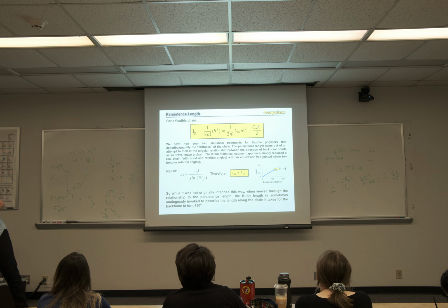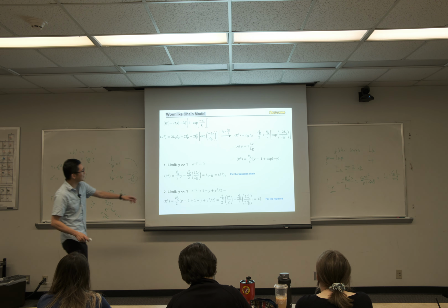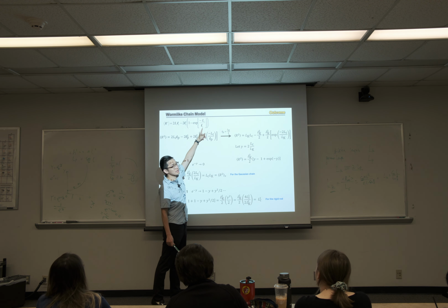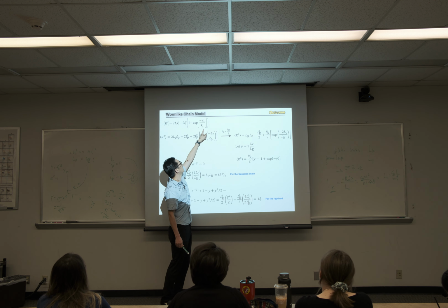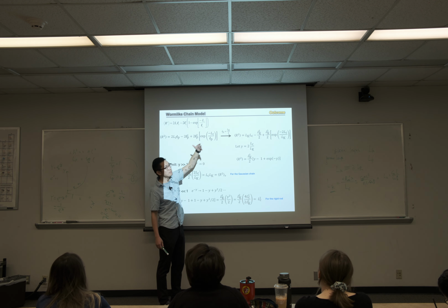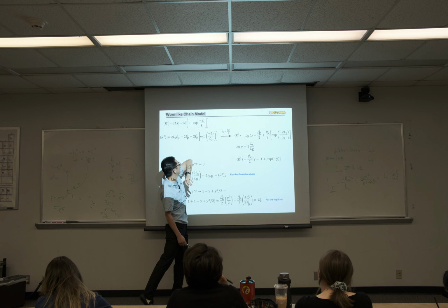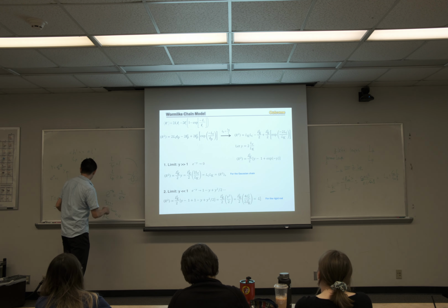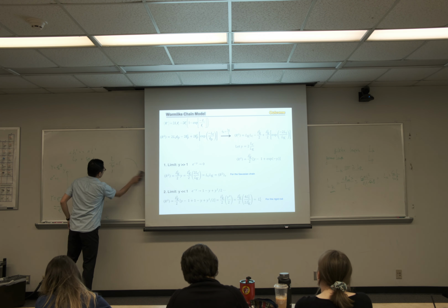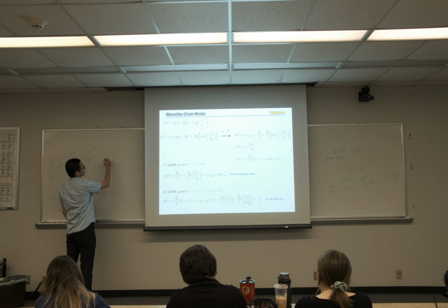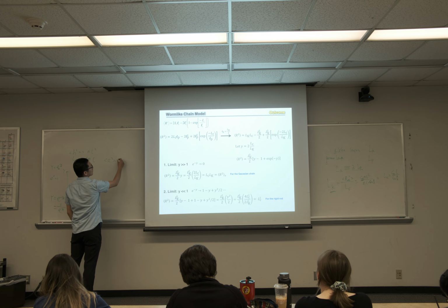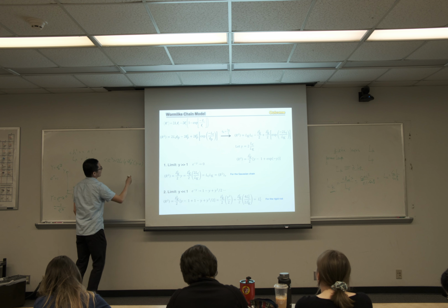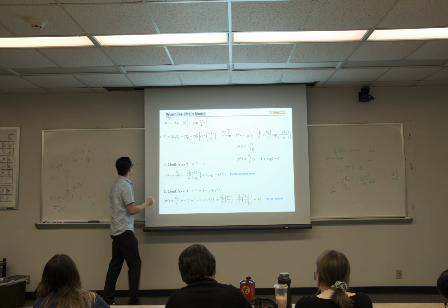Now, let's not dwell on this too much because I want to cover this part. So in the extreme case, this will be LC divided by LP. For a flexible chain, this will be a much bigger number, right? LC divided by LP could be thousands, millions. So this exponential part is basically equivalent to 0. So your end-to-end distance, REE squared, you can simplify this into 2LC LP minus 2LP squared times 1 minus 0, because this is equivalent to 0.